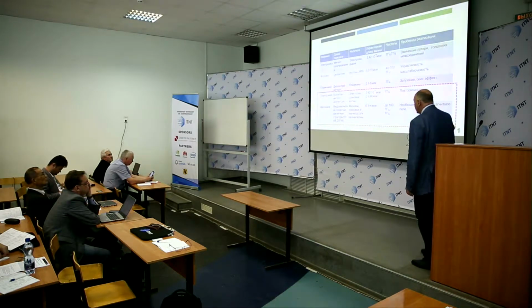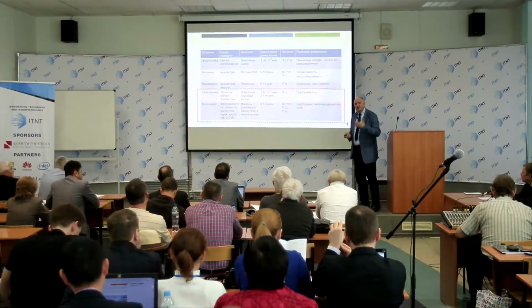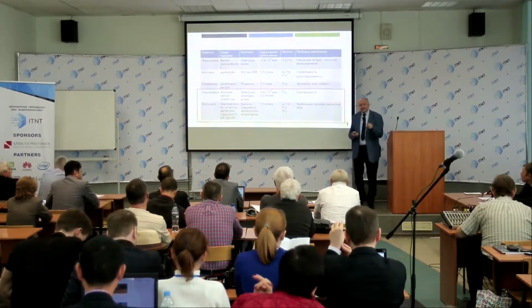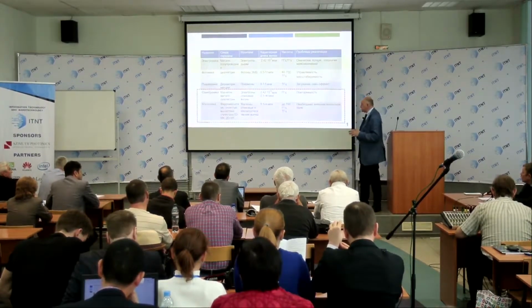So spintronics and especially magnonics. As I already said, wavelengths can be from 0.1 microns, even from 10 nanometers, up to quite long wavelengths. So it's electromagnetic waves, and frequency can be up to 200 gigahertz, and I can show 20, 30 terahertz. In some waves, it is necessary to have an external magnetic field. And this is very bad for all electronics, because the magnetic field can also influence the propagation of electrons if you use conventional microelectronics. However, if you replace ferromagnetic materials by anti-ferromagnetic materials, then in many cases you cannot use or don't need an external magnetic field. Therefore, it is possible to make magnonic devices working without external magnetic field. And this becomes very popular nowadays for investigation and possibly for application as well.